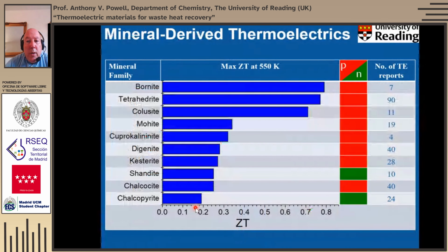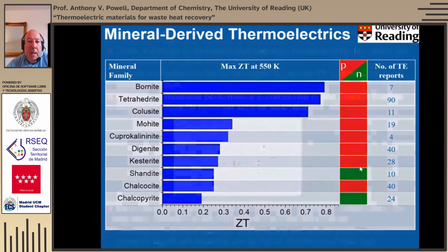So this just shows where some of those materials sit. I'm not going to spend a lot of time on this. I'd like to get to the summary slide in a moment. But just to show that at 550 Kelvin, bornite is probably the best material around at the moment, even better than the P-type tetrahedrites, which have been much more studied. But you'll notice that down here, we're really struggling to get comparable performance out of N-type materials, the ones that have that green box there.